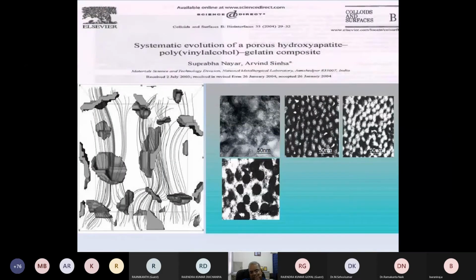Because we were doing this in a polymer matrix, we thought, why should we not allow our mineralized gel to stand for a longer time? Then let the mineralized polymer further cross-link itself without any physical external cross-linker and form a 3D structure. But here we changed the polymer. Instead of PVA, we took gelatin. Gelatin is a denatured form of collagen, which is the bone protein.